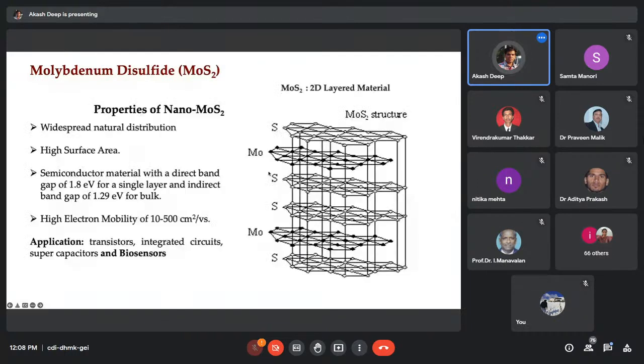So molybdenum disulfide is a 2D layered material. Here you can see the MoS2 structure, and if we separate these layers, one Mo and 2 S, then it constitutes a 2D MoS2 structure. This is also a high surface area material, and it is widely and naturally distributed. So the cost of MoS2 is much cheaper than other nanomaterials like CNTs or graphene.